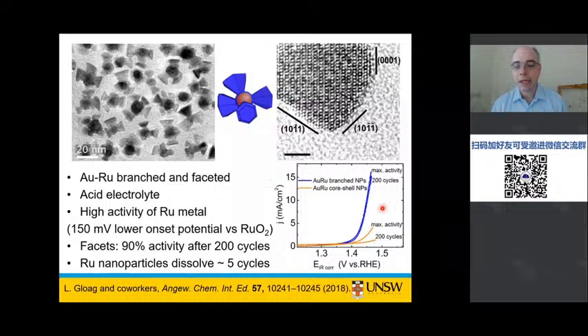So if you have a look here, we can see that we have high activity because, as you would expect, we've got ruthenium nanoparticles, so we would expect to have the high activity. And if we look, say, in terms of how much the activity decreases after 200 cycles, you can see that after 200 cycles, even after 200 cycles, we still have very good activity.